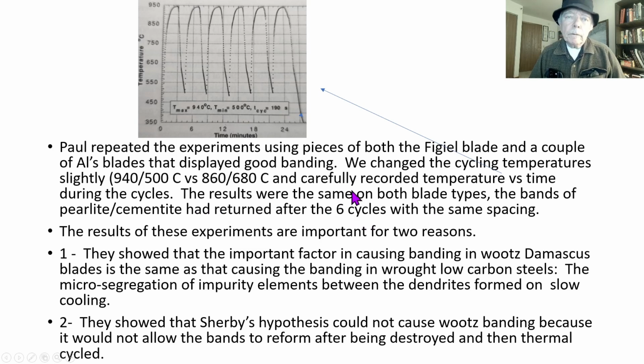The results of these experiments are important for 2 reasons. First, they showed that the important factor in causing banding in Wootz Damascus blades is the same as that factor causing banding in wrought low carbon steels: micro-segregation of impurity elements between the dendrites formed on slow cooling.